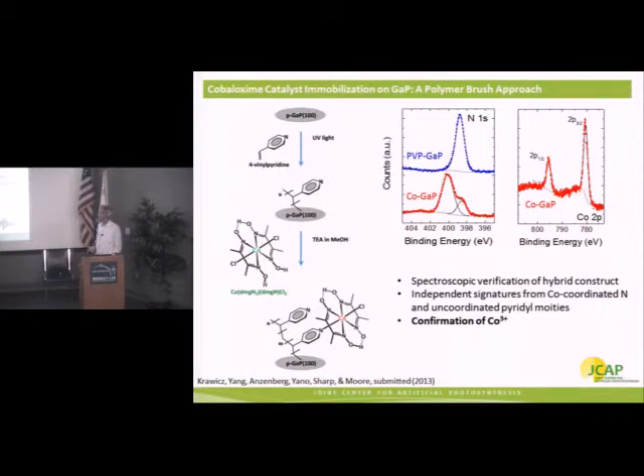Looking at the cobalt itself, we see a typical cobalt spectrum that's indicative of, in this case, cobalt 3+, which is what we would expect for the catalyst bound to the surface. That's indicated by the lack of satellite features in this XPS spectrum and the separation between these two peaks.